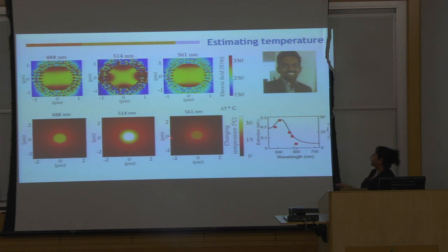So here are thermal maps of the shell and the surrounding medium. So you can see that at the highest point here, the maximum temperature rise is about 40 or 35 degrees, which means the temperature at the surface of the shell is about 60 because this was being held at 25 degrees. So it's not heating it up anywhere close to hundreds of degrees. It's a very low rise that's causing enough for this thing to break. We can also plot the maximum temperature as superimpose on the wavelength absorption plot of the shells, and it kind of follows it really nicely.